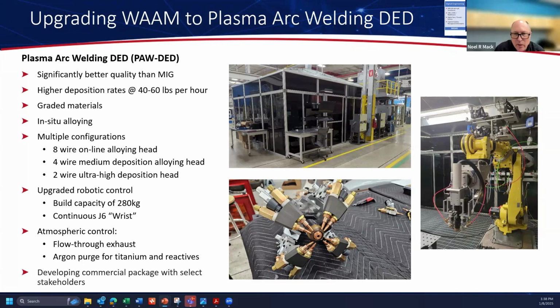In this case, we've actually coupled the two Fanuc robots. So instead of running as 2 6-axes, we're running as 1 12. And you can imagine with a 12-axis system, as well as up to 8 wires being fed and the control of the plasma, there's some extensive programming that goes on behind the scenes to make all of this happen.